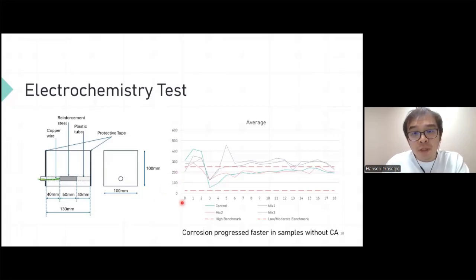After 1 year, so we did 18 cycles here. After 1 year, we see that corrosion progresses faster in samples without CA. So in the chloride diffusion test, we see higher chloride in samples with CA, but also lower corrosion in samples with CA. That's a bit interesting.